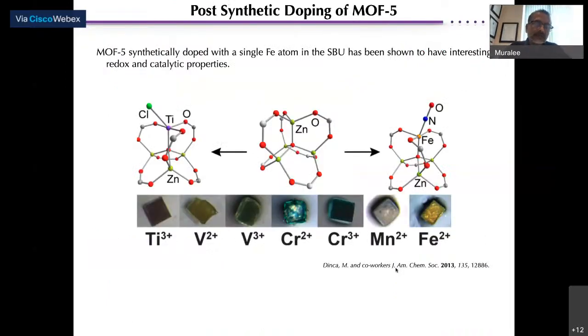So this all started for me when one of my friends, Mircea Dinca, my previous lab mate in Berkeley, started his research at MIT and reported this system while we were also investigating MOF5 for magnetic property reasons. But Mircea was investigating how this MOF5 can be modified. For example, can we replace some of these zinc metal ions with titanium, chromium, or iron, any of these first row transition metals? He was able to show, by soaking for several weeks, if not months, that they absorb and site-replace some of these zinc atoms.